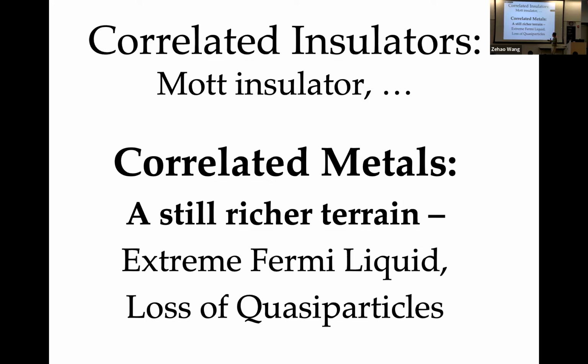So I'm going to cover two such examples. One is that it's still a Fermi liquid, but the quasi-particle weight Z is so small that interaction produces qualitatively new effects. In the cases I'm going to consider, the quasi-particle weight Z is non-zero, but could be as small as 10 to the minus 3. For lack of better term, we're going to call these quasi-particles fragile quasi-particles, the Fermi liquid an extreme Fermi liquid, just to distinguish from the perturbative regime of the effect of interactions.